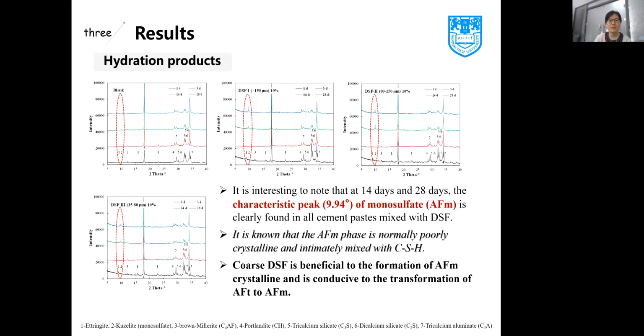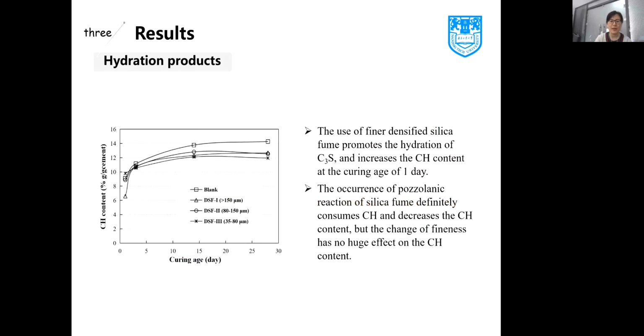We also studied the hydration products of cement paste by using XRD technique. It's interesting to note that at 14 days and 28 days, the peak of monosulfate is clearly found in all cement paste mixed with densified silica fume. It's known that the AFm phase is normally poorly crystalline and intimately mixed with CSH. Coarse densified silica fume is beneficial to the formation of AFm crystalline and is conducive to the transformation of AFt to AFm.